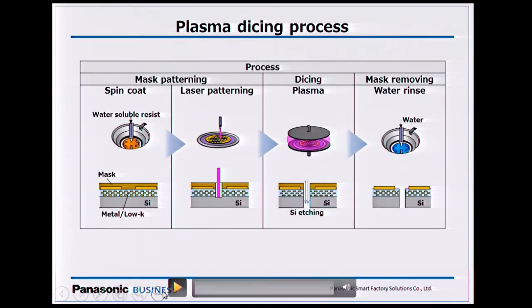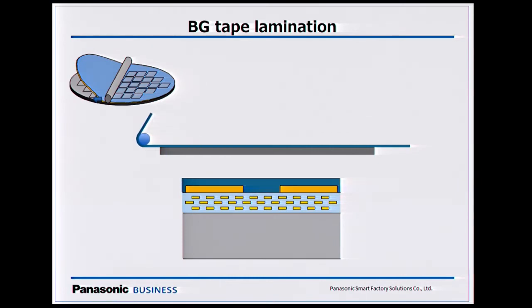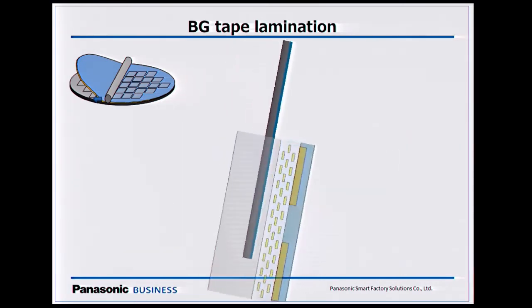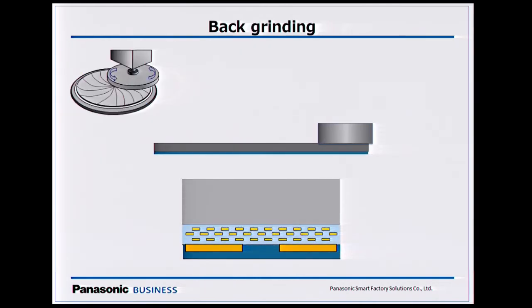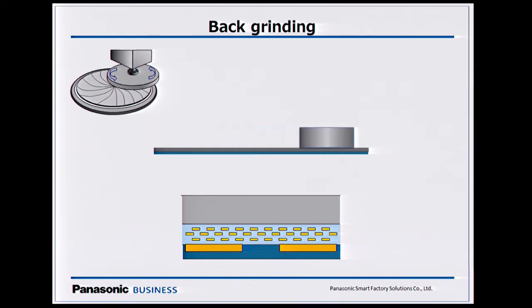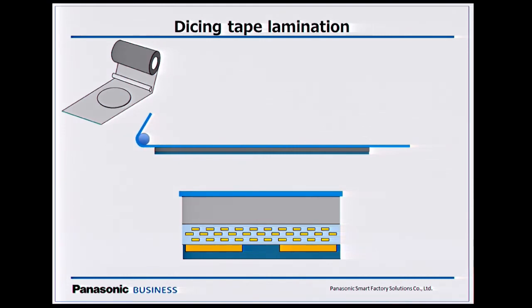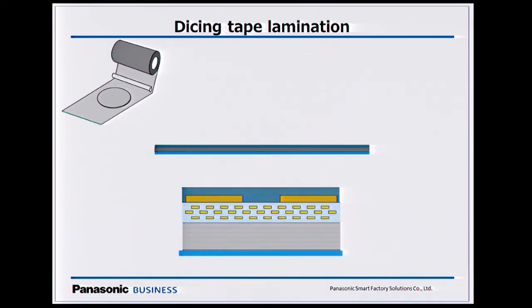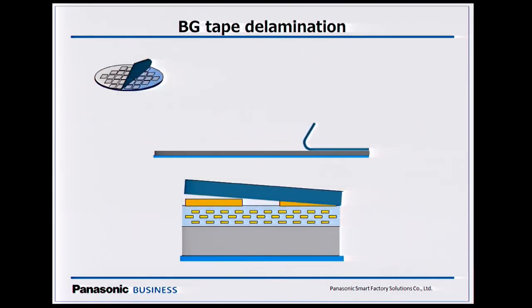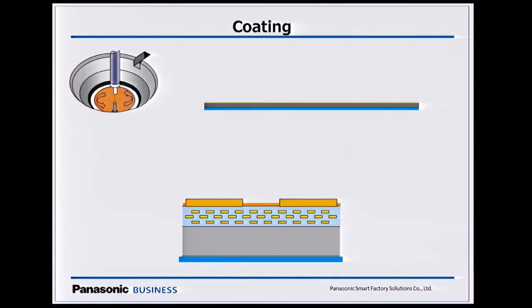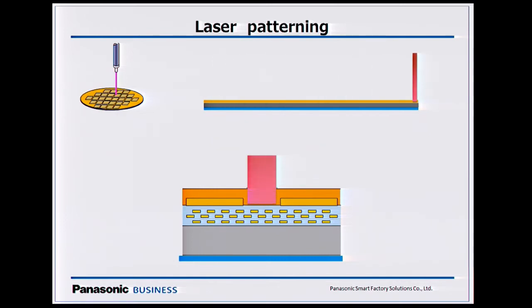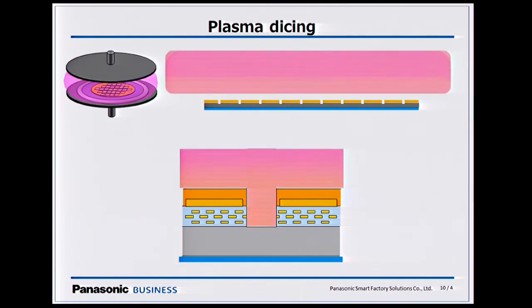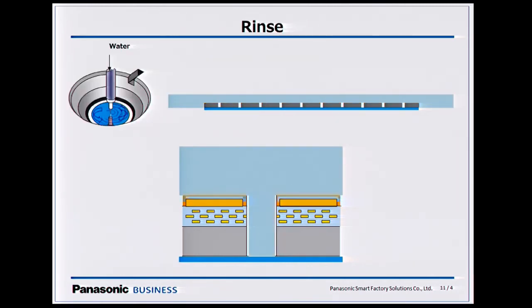I'll just show you one more. It's the last one, but it's highlighting the easier step of using the water-based resist or pattern. In this case, we have to spin or spray coat the water-based resist on top. Again, dicing through, etching through the metal, and then put it inside the plasma chamber. But the difference with this one is it's water-based, so relatively easy. Just wash it off and take any debris with you as well.